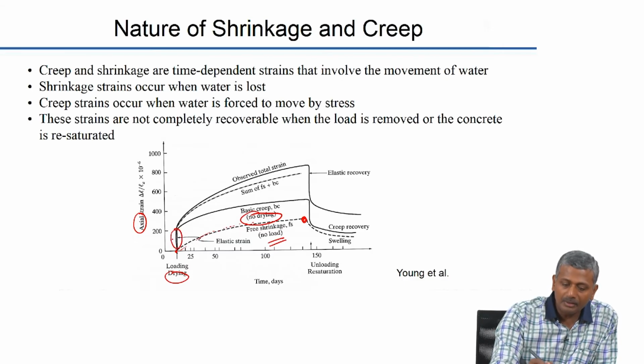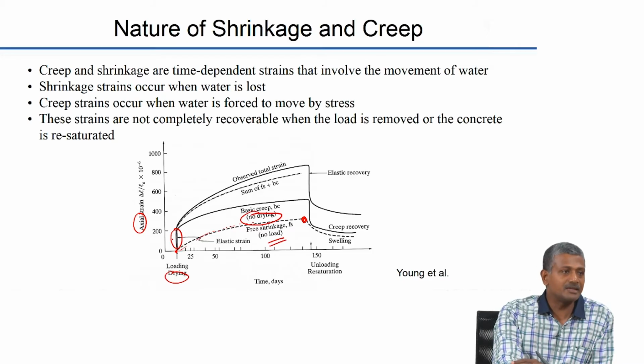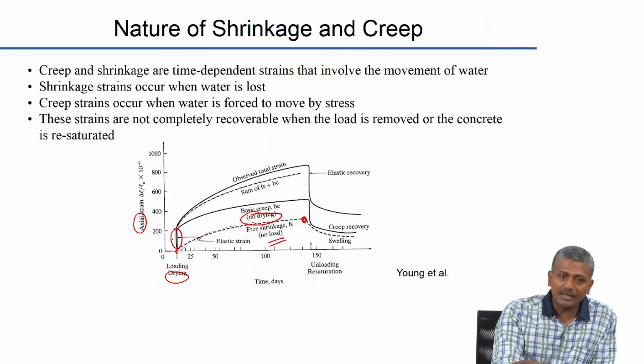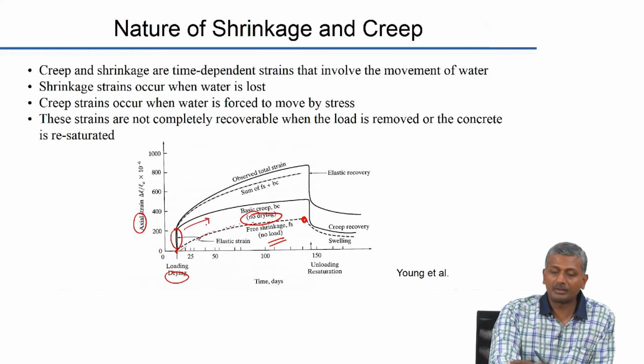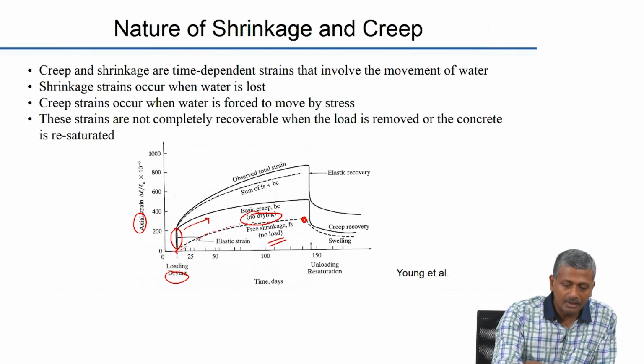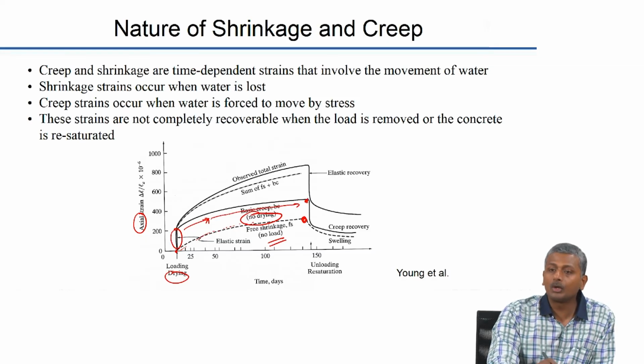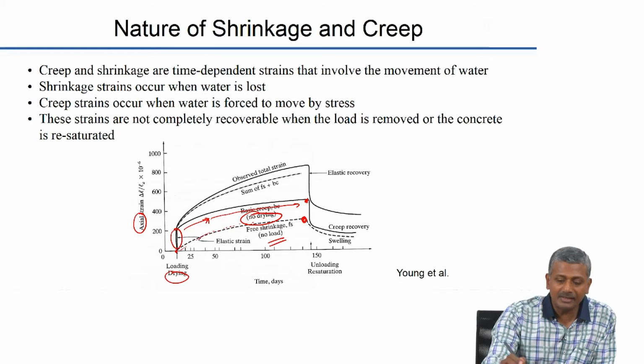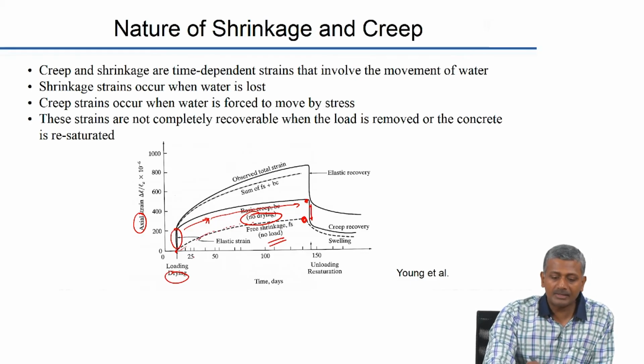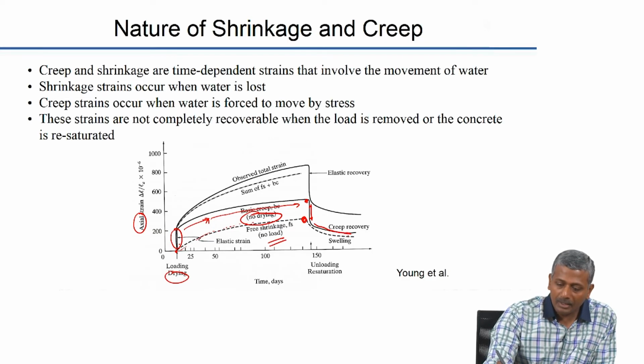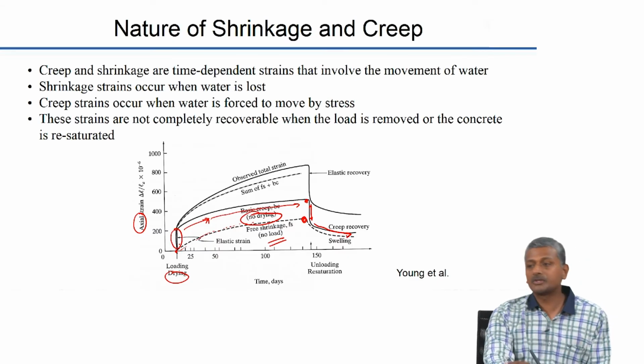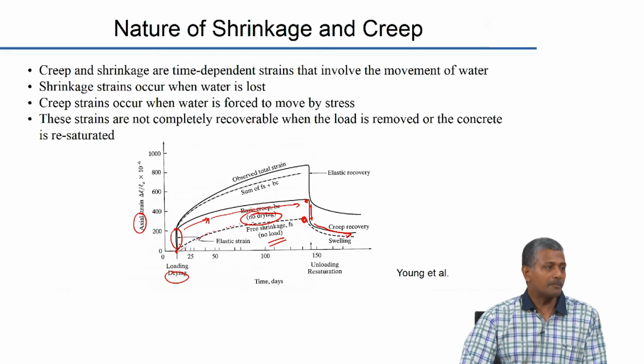As soon as you load the material, you get an immediate strain, that is basically the elastic response of the material. With time, you get the time dependent response of the material. So, even when there is no drying, creep can happen obviously because of loading. You have the elastic strain and you have the time dependent creep strain which keeps on building up in the material. At a given point, when you unload the material, what happens? It instantaneously recovers the elastic strain, but then it cannot recover fully the strain which was associated with the time dependent factor. So, some volumetric deformation is built into the material.